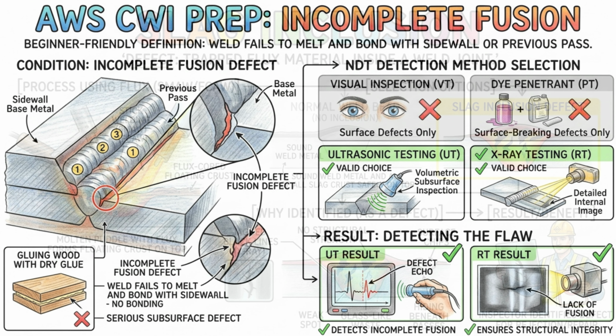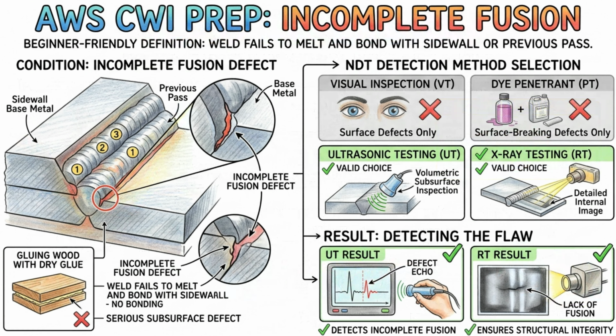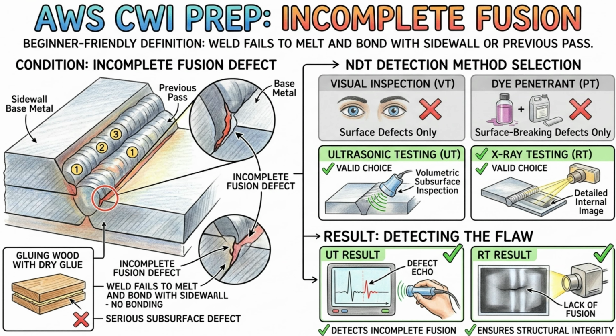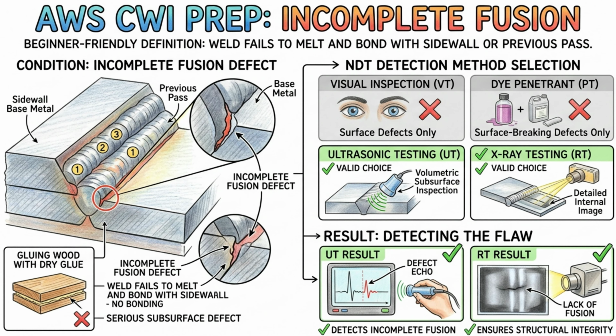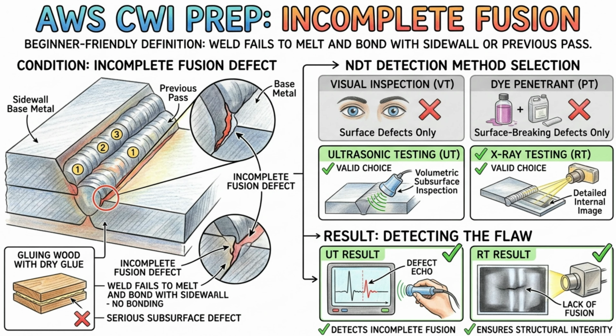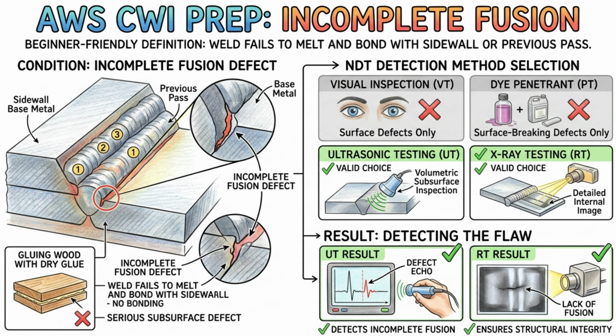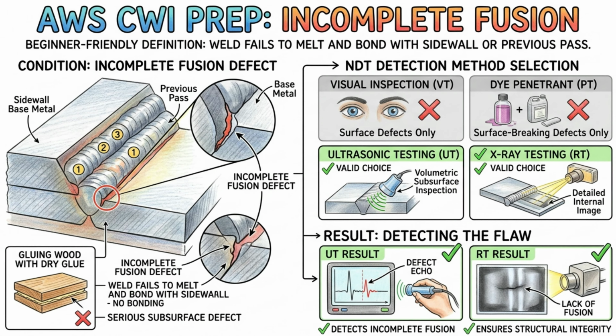Incomplete fusion is one of the most serious internal defects a welder can make. This happens when the welding arc fails to completely melt and bond with the sidewall of the base metal or the previous weld pass. Imagine trying to glue two pieces of wood together with dry glue sitting between them, and you have a clear picture of incomplete fusion. Because there is literally zero atomic bonding across that interface, an inspector must use ultrasonic testing or X-rays to catch this dangerous structural flaw.